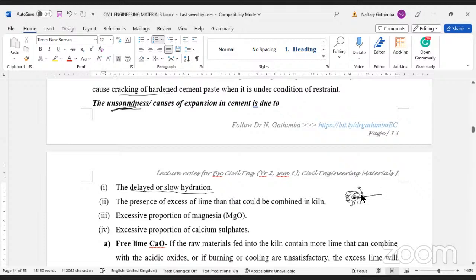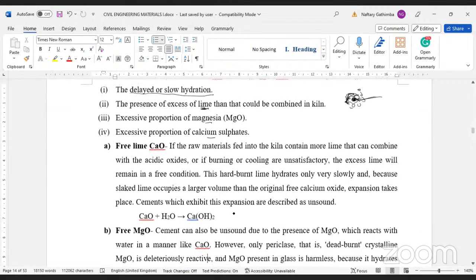Water takes time to penetrate in here. So that slow rate of hydration means the outer material has already hardened and gained strength, but inside there's still reaction. And you see, when water comes into contact with calcium oxide, they expand as they become hydrated. So this may cause unsoundness of cement. Also the presence of excess lime, magnesium, and calcium sulfate. And that one I have explained here, what is happening.